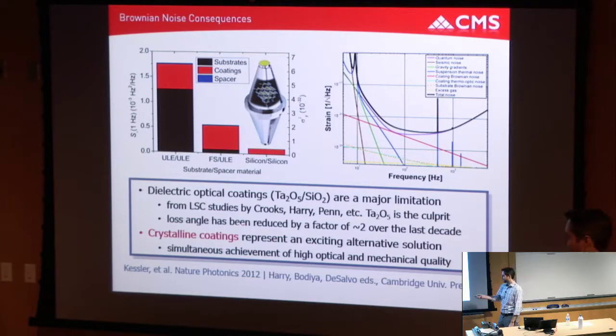They've worked very hard to reduce the loss angle in this system by actually alloying the tantalum pentoxide layer with titania. Titanium dioxide has a higher Q, but the problem is it brings additional optical losses. So this is a fine balance of keeping the optical quality good, but increasing the quality factor. And so they've gotten it down by a factor of two since, say, the late 90s, early 2000s.